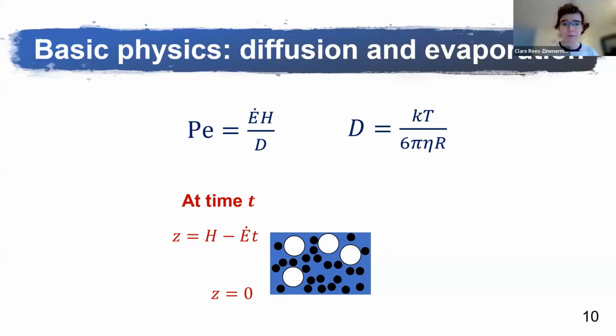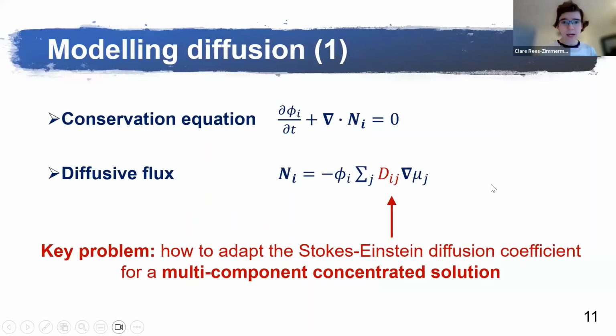We characterize this playoff by the dimensionless group, the Peclet number, giving the ratio of evaporation to diffusion based on the Stokes-Einstein diffusion coefficient, D. You'll note that D is inversely proportional to the particle radius. So we'd therefore expect that larger particles would diffuse more slowly, and so would stratify to the top surface. But this wouldn't explain our experimental observations of small particles stratifying to the top surface, which suggests that we may need to include some other phenomena in our model. To start with, though, I'll just model diffusion, but then we can later discuss adding other phenomena.